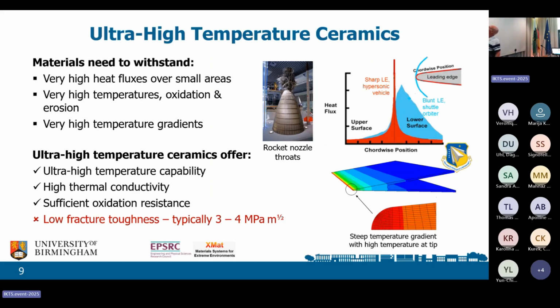So this is heat flux against position on that curve, and you can see the pale blue one is fairly gentle. There is a peak, but it's a fairly gentle one. But look at that red one. Absolutely. Very, very, very localized high heat flux. What that means is that if this is your leading edge, this is the bit that gets really hot. And if you then model that, actually it's this bit of that, and the whole of that is that. So it really is just a millimeter or two that's actually getting to the maximum temperature. And it's going to get there very quickly. So the heating rate is going to be very, very fast.